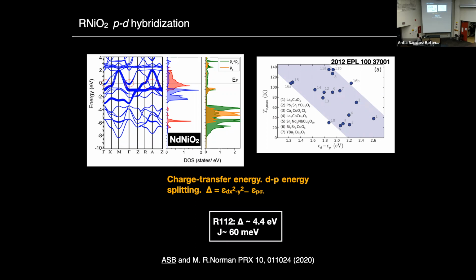And you can instantly see why over here. This is just the nickel D density of states for a couple of orbitals, the dz square and dx square minus y square. This is the oxygen P. You can see that these states are very far apart. If you were to look at a cuprate, they are much closer together. So the charge transfer energy is larger. That translates into a superexchange that is still sizable, somewhere around 60 meV. But remember that in cuprates, you were around 120, so much smaller, which may also account for the lower Tc that you have in this material.